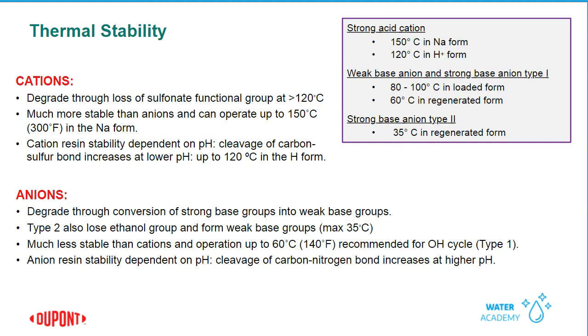All resins aren't the same when it comes to thermal stability. For example, if you look at the chart on the top right of your screen, strong acid cation resins are much more thermally stable than anion resins. They can withstand up to 120 C in the hydrogen form before there's going to be any effects of degradation. Also, strong base anion resins, even weak base anion resins, you can assume that 60 C in the regenerated form is a temperature that you don't want to exceed when it comes to anion resins.